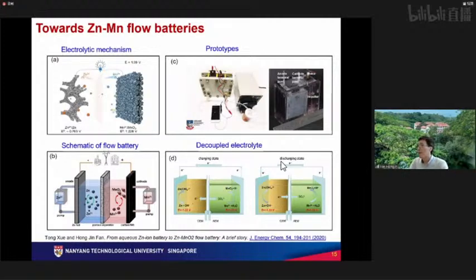alkaline, whereas the cathode side can be slightly acidic, because if the whole thing is too acidic, the zinc is unstable. So if they decouple the electrodes on both sides, then you can eventually increase the overpotentials and get a very large voltage, beyond even 3 volt. Okay, if you put in two membranes, with an aqueous electrolyte between, it can even go beyond 3.4 volt. So this is kind of engineering. It's a very innovative method to realize high voltage.